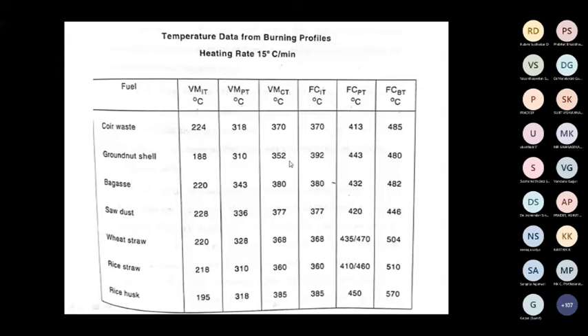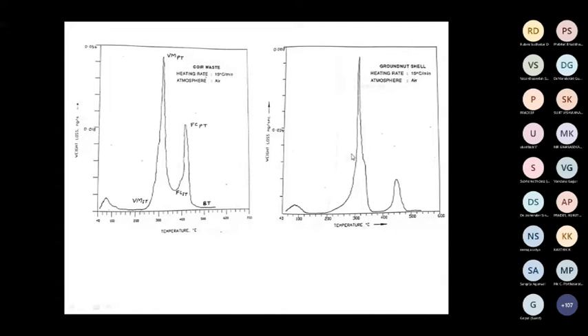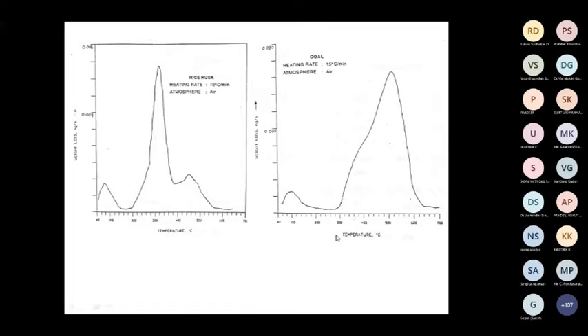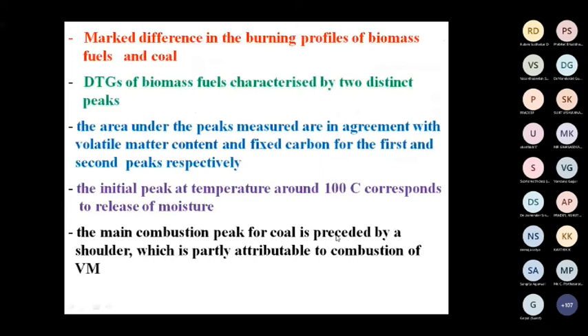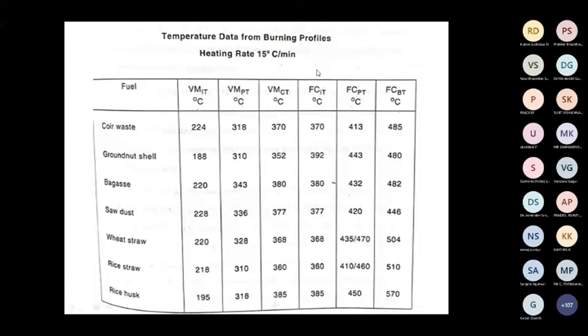That's one thing we can see visibly, and that's what I have shown you. Definitely, there is a time lag between groundnut shell VM combustion and the combustion of fixed carbon. That's what is shown here. Then among the fuels, fixed carbon burnout for rice husk is the highest. Complete burning, the final temperature, is 570 degrees compared to the others.